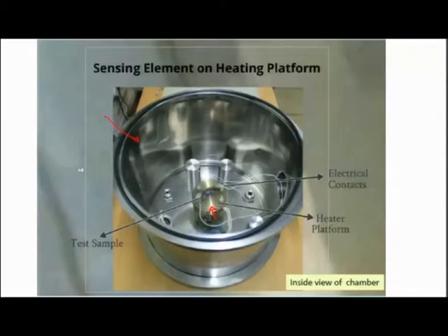So there is also going to be an air inlet and outlet, where there is an evacuation step followed by a carrier gas, which would otherwise be an inert gas, in which we can selectively inject, through very precise mass flow controllers, ppm levels of hydrogen. As the concentration in the chamber varies and we allow some diffusion time to happen, we observe the response behavior of this element based on such changes.